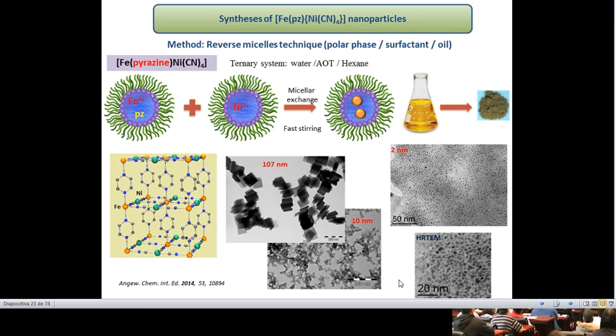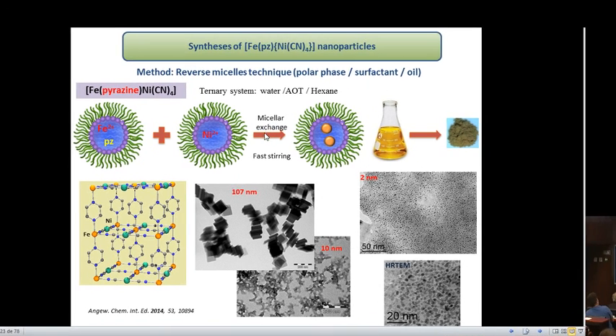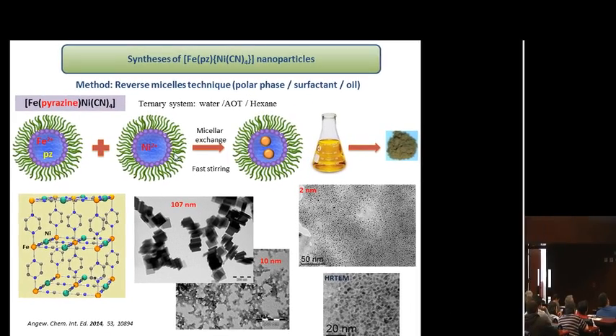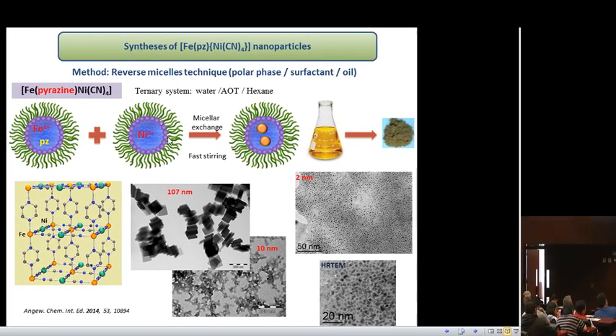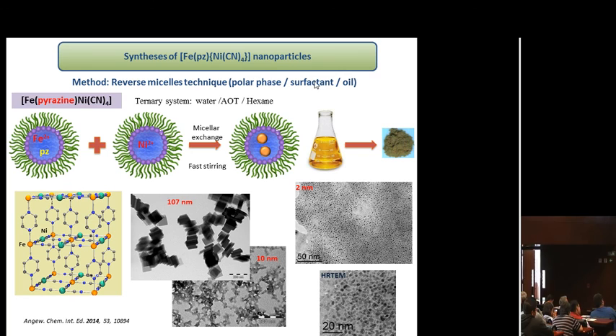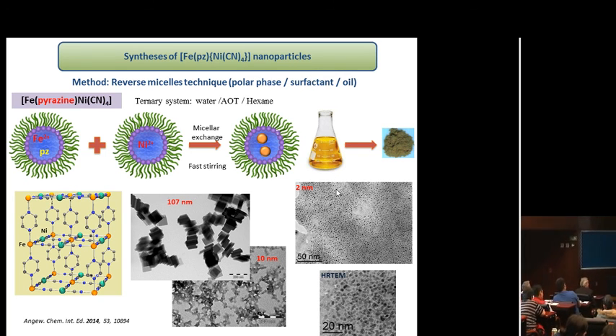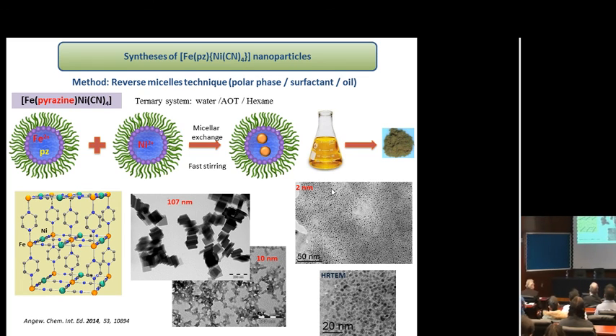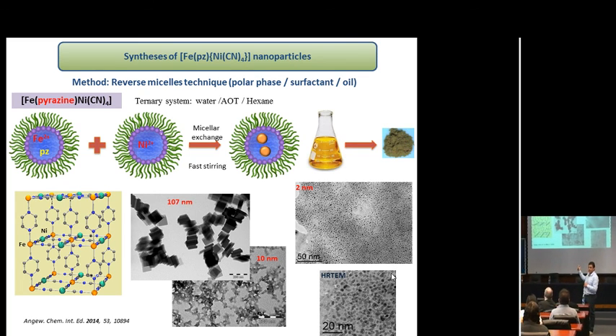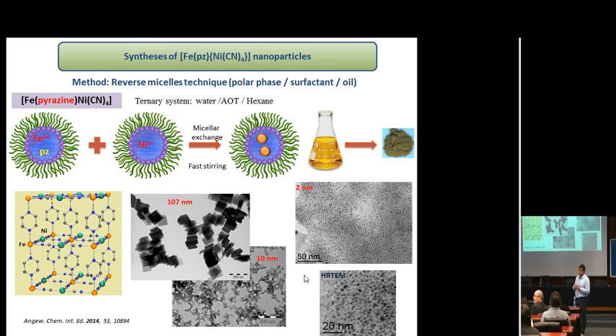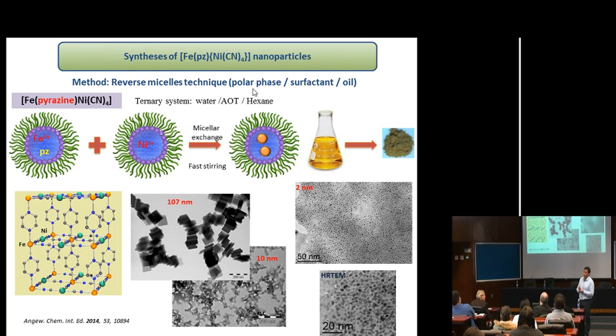Is there an effect on the crystal structure because of the hysteresis? I mean, when the spin crossover occurs, are there different crystallizations, or is the structure the same? It depends on the compound. Sometimes you have no structural phase transition, sometimes you have phase transitions. In this case, you have no structural phase transition for the clathrates. But it's really dependent on the system you use.